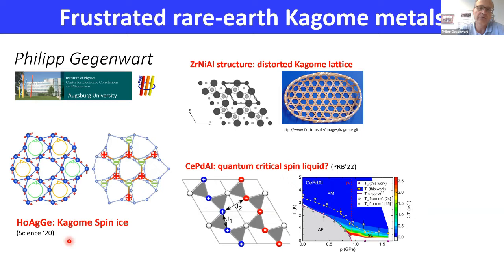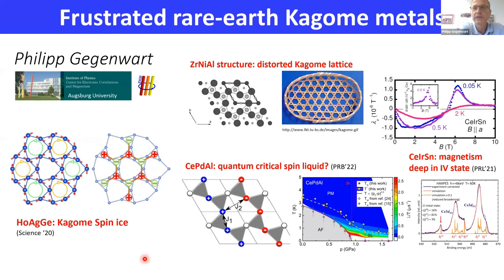One is that for the heavy fermion cerium palladium aluminium, we see a broad pressure range where new microscopic experiments indicate spin liquid behavior, and where we also see indication for quantum criticality. The last topic of my talk will be a material cerium iridium tin, where we have a much higher Kondo interaction. So there we are deep in the intermediate valence regime, and fascinatingly, at temperatures and energies more than 2 orders of magnitude below the characteristic valence fluctuation energy, we see the emergence of antiferromagnetic moments at low temperatures. That may hint at the competition between magnetic frustration and Kondo singlet formation, and could be an indication of a possible Kondo breakdown in this material class.